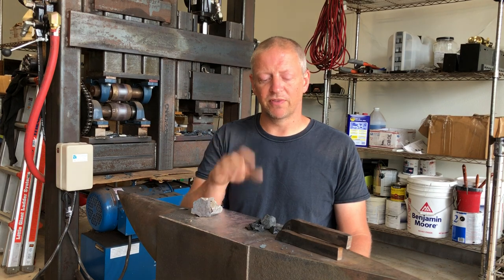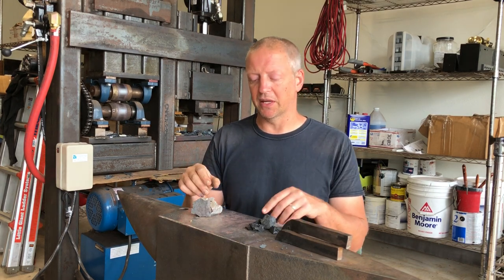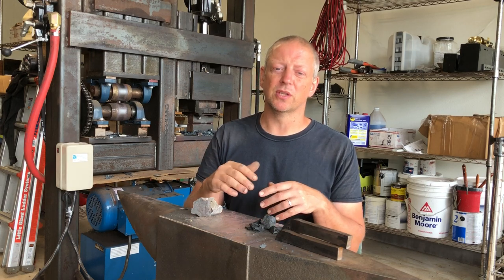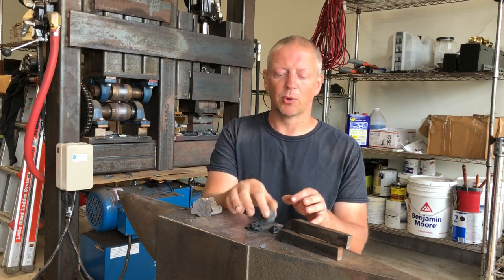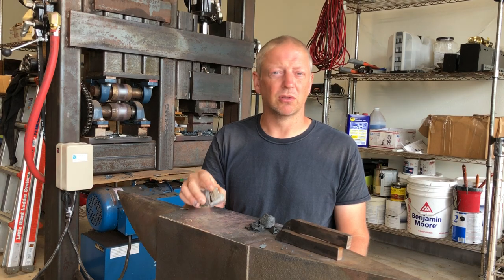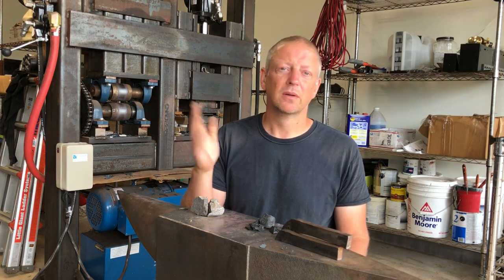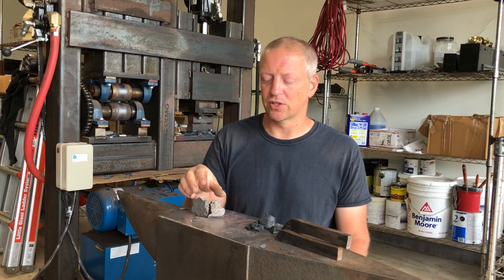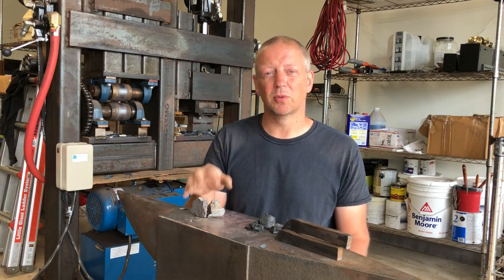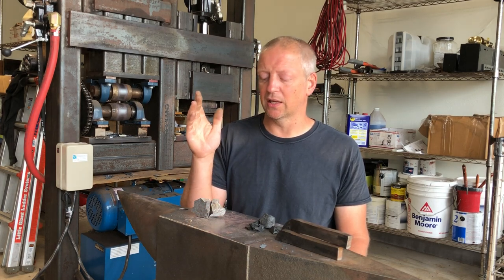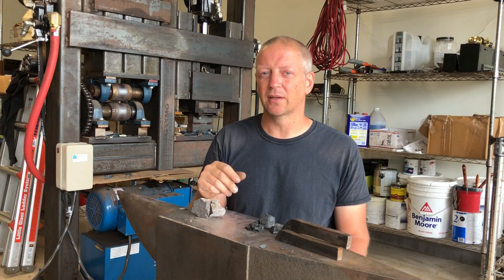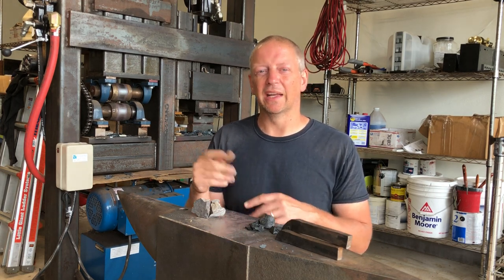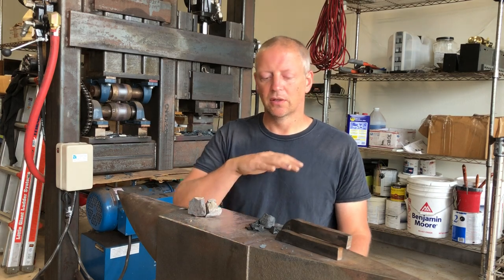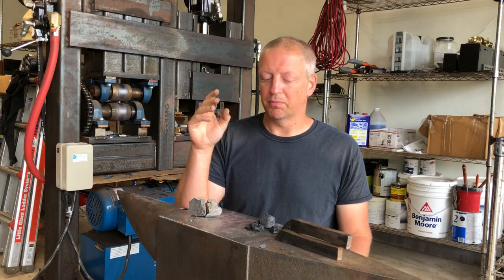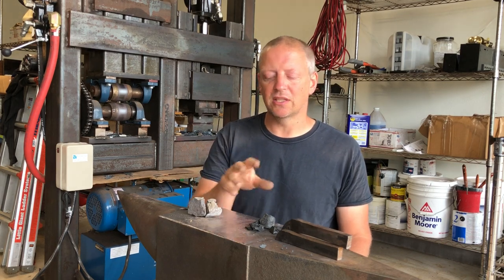These two get used very differently in the crucible steelmaking process. I'm going to assume that you are using a combination of a carburizing agent and mild steel. You can use wrought iron, you can use bloomery iron, whatever. It doesn't matter, it just changes your calculations. Using wrought iron or bloomery iron does have one disadvantage in that, again, you don't quite know what you've got. You're adding a variable to your chemistry. But all things being equal, these are used very differently.